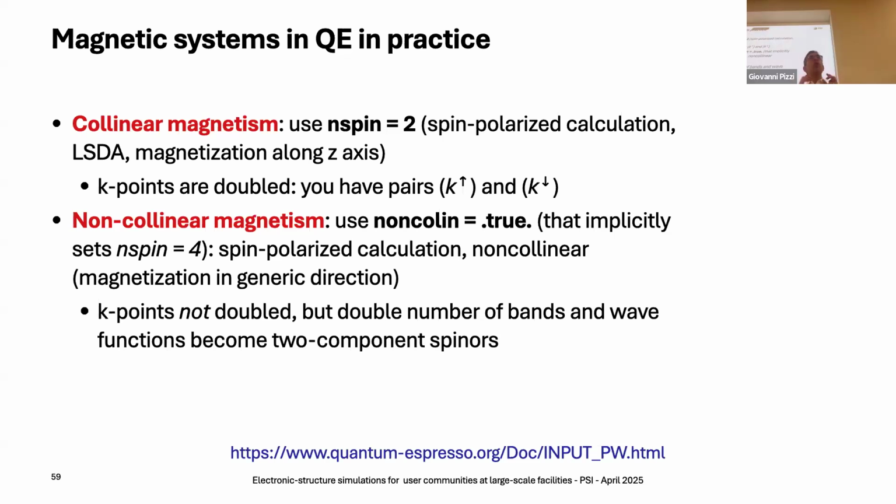When you start doing antiferromagnetic systems with non-collinear spin, the energy landscape is not very smooth, it's very complicated. There are a lot of small minima, with very small energy differences between them. If you don't start very close to the minimum, so you don't already know more or less what you want to do, and even in those cases it's not easy if you have a lot of different complex configurations, the code might not converge, or might converge to a local minimum, which is not necessarily the ground state.